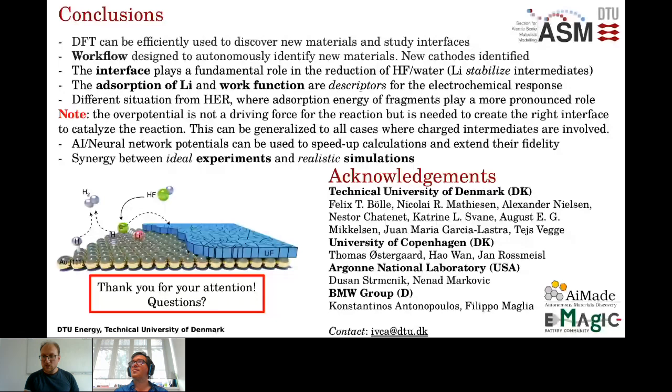Okay, so more on the funnels approach, does the input structure need to be previously relaxed? In this case, we take the structure from the ICSD database, so in principle they are structures that are already known. What we usually do is relax them as a first thing, and then we create the different structures that are needed. This was our approach to speed up the search, but in principle, you could also create the structures on the unrelaxed side, and then of course relax them afterwards. But to get good properties, you need to relax the structure, and you need to be sure that you're relaxing it with the right potential. The exchange correlation functional should give you a good estimation of the lattice parameter and at the same time maybe good energetics.